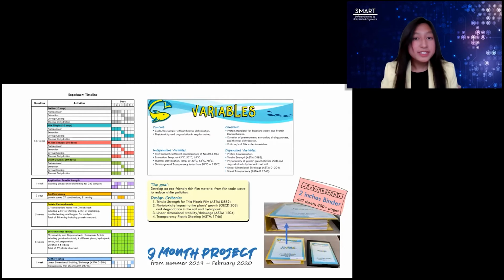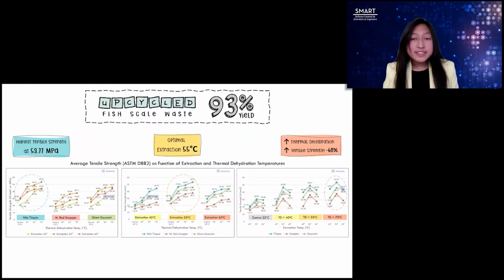And after 9 months and hundreds of trials, my results are promising. I successfully upcycled fish scale waste with a 93% yield into a thin, translucent, plastic-like film, reaching tensile strengths up to 53.77 newtons per square millimeter. The optimal extraction temperature was 55 degrees Celsius, where tensile strength peaked, and thermal dehydration was proven to boost tensile strength up to 48%.